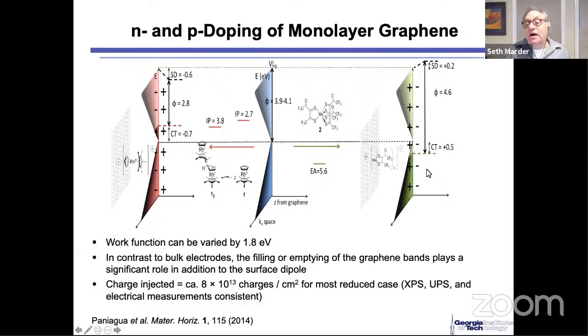And you can do the complementary thing with p-dopants. You can p-dope these and deplete the valence band. By doing this, in this particular case, we varied the work function by 1.8 electron volts. And in another case with Antoine, we can extend that to over 2 volts. So by and large, we can take graphene, one material, p-dope it, and make it a much better hole injection material. Or we can n-dope it and make it into a very good electron injection material.